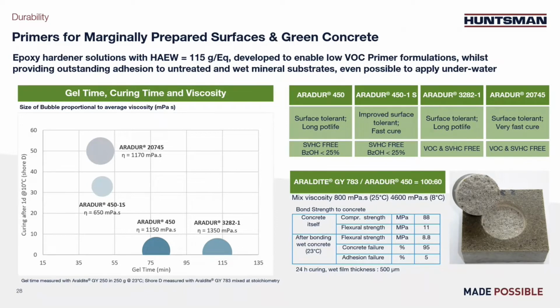Those products are made in a way that they even cure well underwater. And this ability of curing underwater enables the application on green or fresh concrete. Basically, no need to wait for the full cure of the concrete. It is possible to apply the primer as soon as you can work on the new concrete. It also allows to seal the concrete so it can cure without water evaporation, which helps for the quality of the concrete afterwards.